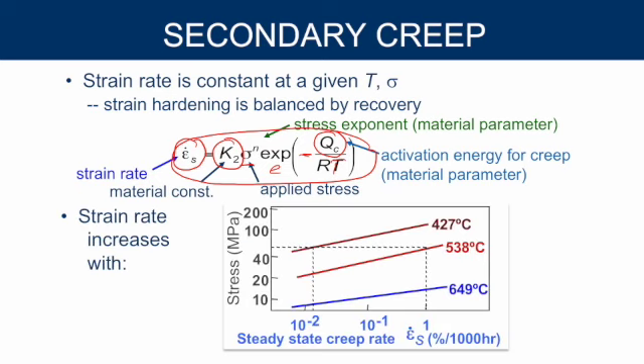So what does that look like if we graphed it out? If we take the natural log of each side, we can get a straight line, right, which has a constant slope. So the word I just used may be useful for the question I asked previously. And as we see, as temperature increases, the amount of stress needed decreases dramatically, which means the strain increases dramatically with temperature. So you need less stress, you get more strain. That's what this equation says, right? Exponentially increase in strain. The other way to look at it, since this and temperature are on the same side, they're inversely proportional to each other.